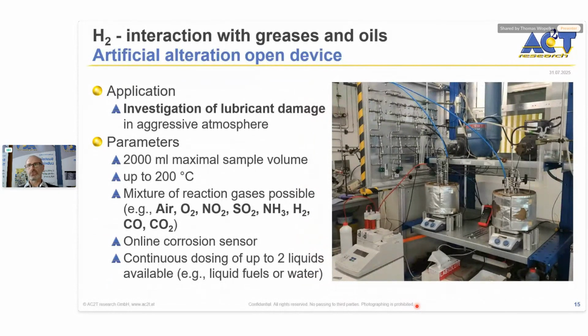What we also do is artificial oil alteration of the lubricants we investigate. So we can see here a reactor device. This is a chamber which you can fill with the lubricant of interest. And through this lubricant, you can flush different gas mixtures. You can flush it with air, with oxygen, with NO2, SO2, H2, NH3. You can use up to 4 different gases at the same time, and you can also dose in 2 different liquids to this chamber. And due to the heating and the mixture of these gases and liquids, the lubricant ages and changes its properties.